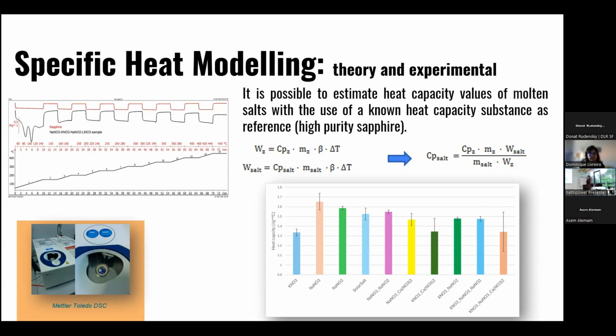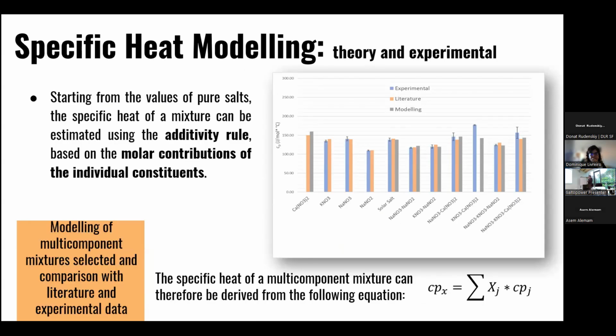The specific heat, as you know, we measure with a differential scanning calorimeter. It is possible to estimate the heat capacity of an unknown molten salt with the use of a known heat capacity system, and we use high purity sapphire as a reference. Here we reported the results as an average of more than 25 repetitions of measurement for each mixture. I reported also the experimental error, because as Thomas said, it's not so easy to determine the exact value of these characteristics. So we tried modeling to predict the heat capacity of a mixture, starting from the values of the pure salts that we determined before. We use an additivity rule that is based on the molar contribution of individual components.